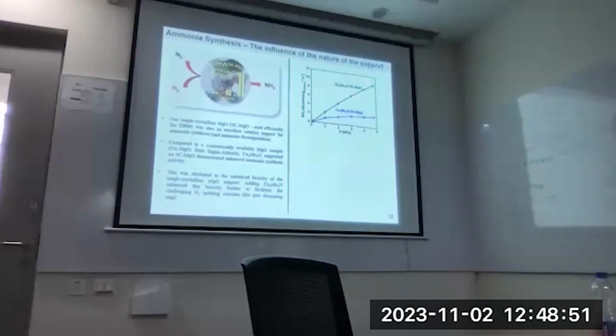Here what we realized is because this cobalt molybdenum nitride interacts with the magnesium oxide and forms a more basic catalyst. The surface of the catalyst is more basic. So we measured this basicity using CO2 adsorption. And that's why for this particular process, you need to have a more basic surface for it to be facilitated. Especially the molybdenum acts as a very good site for the nitrogen to split into individual nitrogen atoms. Otherwise, it's a very difficult activation.